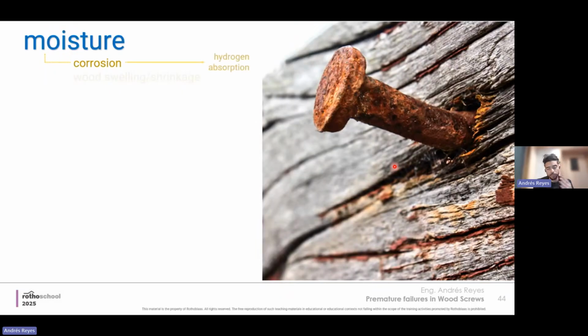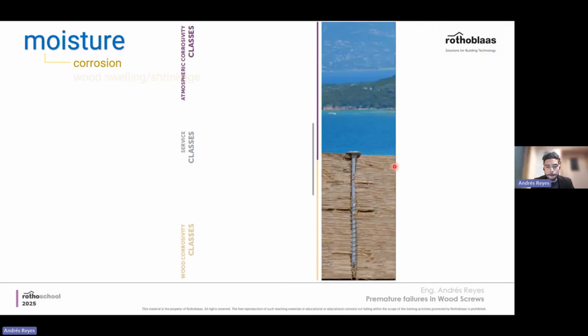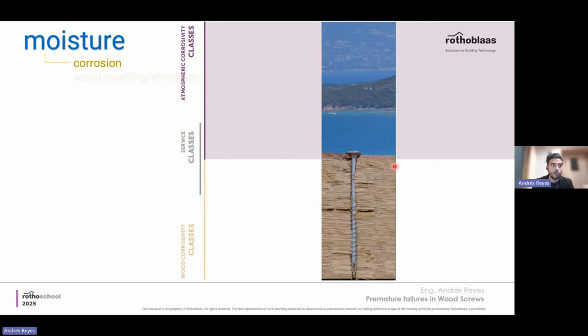Let's talk about corrosion. And then hydrogen absorption through corrosion, which the proper term would be cathodic hydrogen absorption. There are three types of exposure that we need to talk about. The first one would be the atmospheric exposure. So how aggressive is the environment? It would affect mostly the exposed part of the screw. I wouldn't say this is not relevant, but this is less relevant, as we saw in the picture at the beginning of the presentation. The corrosion tends to happen in these types of failures in the inside of the screw.